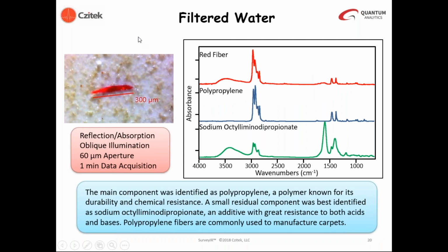Our next example is also a filtered water sample. And in this case, we're viewing a relatively small red fibrous material directly on the surface of the filter paper. So we're viewing this once again in oblique illumination, and you can see the size of the microplastic is roughly 30 micrometers by 300 micrometers. In this case, we removed the particle from the filter paper, placed it directly onto a low-E glass slide, flattened the material, and analyzed it in a reflection absorption mode. So we're reflecting off the surface of the low-E glass through the fiber material using a relatively small aperture in this case, 60 micrometers, and a 1-minute data collection.